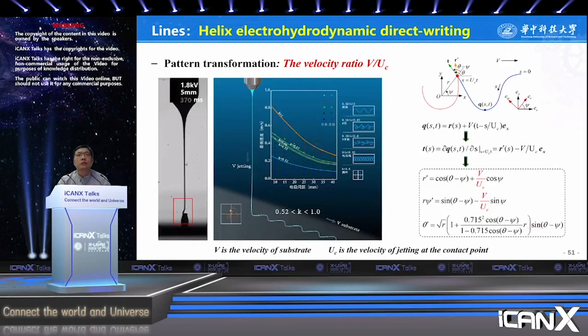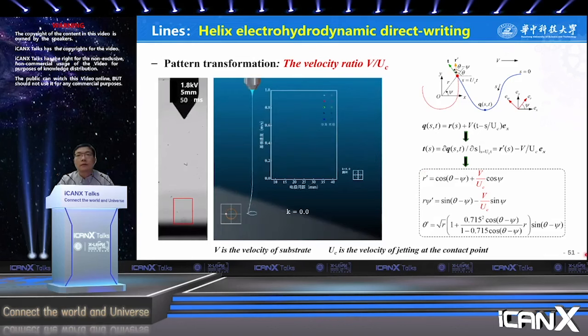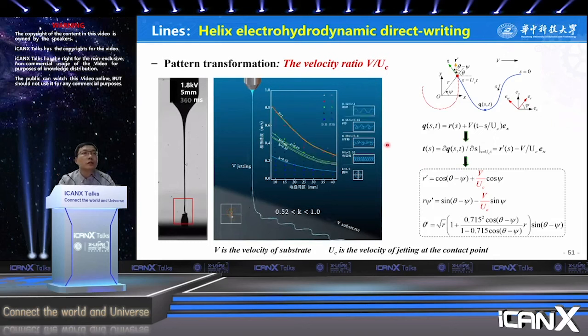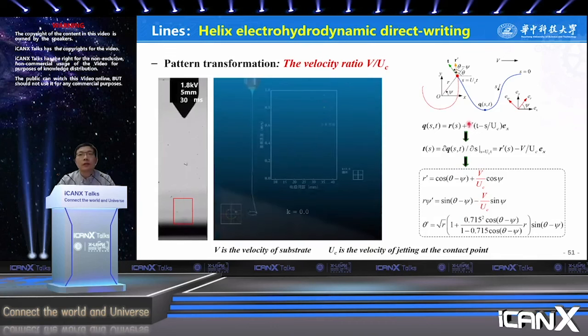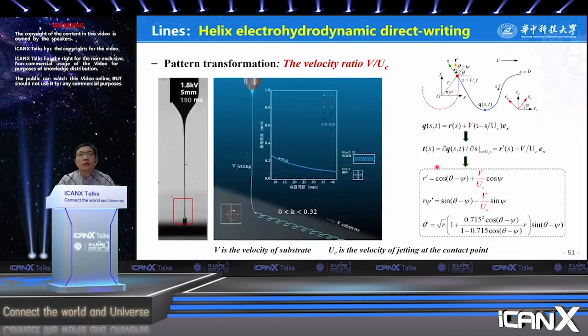In the geometrical model, the deposited trace on the collector becomes 5 kinds of structures. It's related with the velocity ratio. V is the velocity of the substrate. UC is the velocity of jetting at the contact point. We established the equation to give the pattern theoretically. Meanwhile, the critical value for the transformation of the patterns are given.